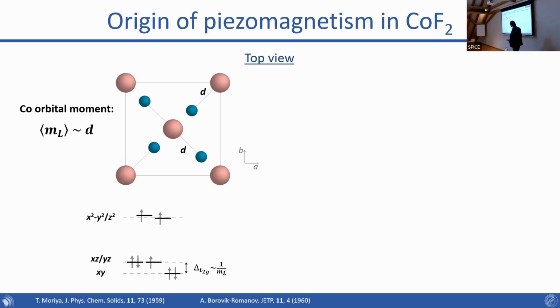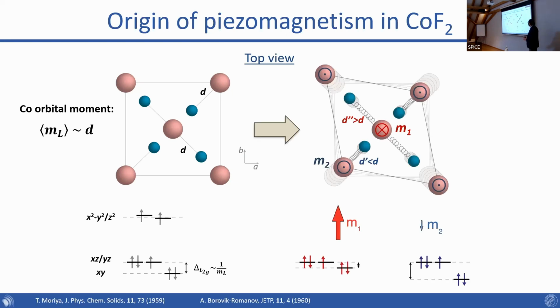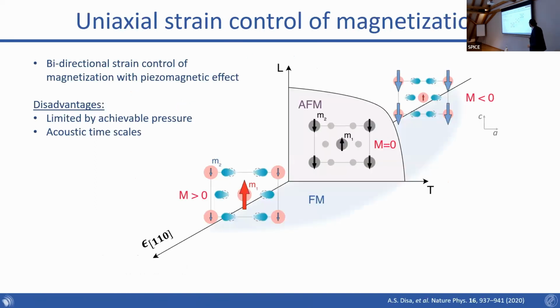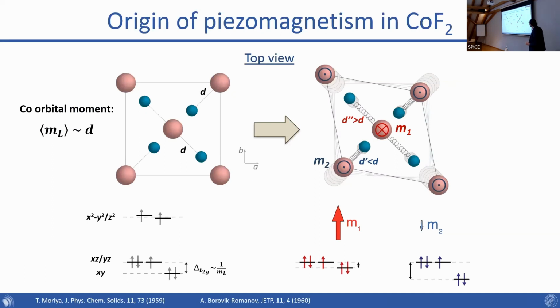And so, roughly speaking, the orbital moment at the end of the day is proportional to the in-plane cobalt fluorine bond length in this material. In equilibrium, the two sublattices have the same in-plane cobalt fluorine bond length, d. So you have the same orbital moment here and here, and this compensated antiferromagnetic structure. Now what happens when you strain the material is that one of the bond lengths gets longer and the other one gets shorter, right? So the crystal field changes in such a way that the orbital moment gets bigger on one side, smaller on the other side. This is the origin of this decompensation. Okay, and so this is what is giving you the piezomagnetic effect.